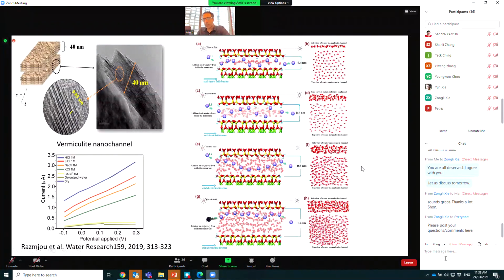So what we found is very interesting. It was that when the nanochannel size is above 1 nanometer, ions usually use one surface charge, one of the walls, nanochannel wall, to transport. So it just follows the surface charge transport. Whereas when we reduce the nanochannel size to below 1 nanometer, the ions transport in a zigzag fashion. That was very interesting because this zigzag movement rate of lithium was higher than the other ions. So that gives the basis of lithium selectivity.